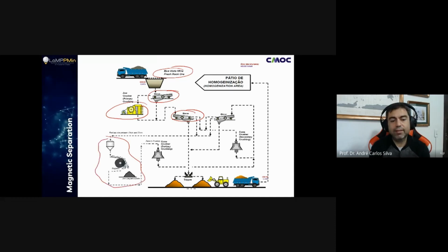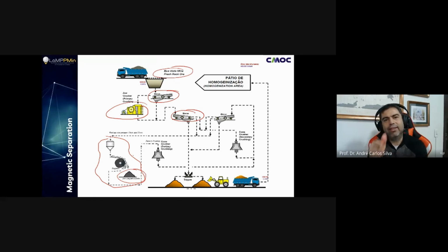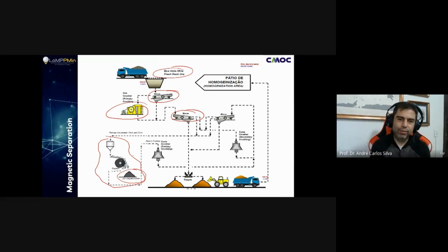Okay, this is a magnetic separator, and here's the trick. I don't want the non-magnetic material. The magnetic material is directly associated with the rock that's going to be bearing the minerals carrying niobium. So it's quite complicated. No, it's quite simple. We have a rock called nelsonite, and nelsonite is going to bear niobium, and nelsonite has magnetic properties. So we did this first cut, and the non-magnetic material, we just throw it away. We don't want it, and those non-magnetic particles are normally composed of silicates.